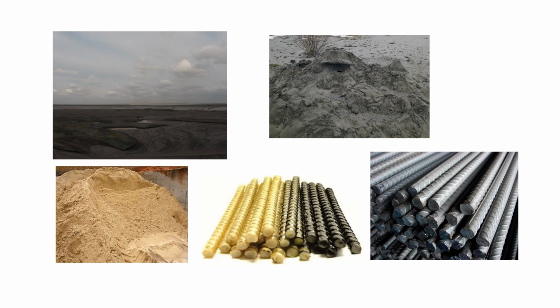At the same time, industrial waste from iron ore enrichment, the so-called tailings, is used as a fine aggregate to replace quartz and construction sand. Studies show that a 40% replacement of quartz sand with fine iron ore dressing waste is optimal for the manufacture of concrete mixtures without any adverse effect on strength and durability properties. The paper considers the stress-strain state of beams in the second group of limit states made of concrete mixtures at 100% replacement of quartz sand with fine tailings.